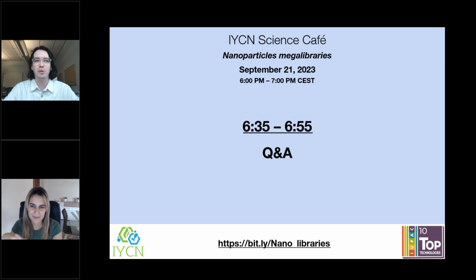In that example, what we would do is try to replicate the synthesis of a gold, palladium, copper nanoparticle on titania at milligram to gram scale instead of the single nanoparticle scale. So the synthesis scale-up challenge is pretty large. The next would be applying that material to a large scale application: can we do large scale water purification with photocatalysis in this material? So definitely scaling it up and doing more traditional testing so that you can then compare it to literature results as well.